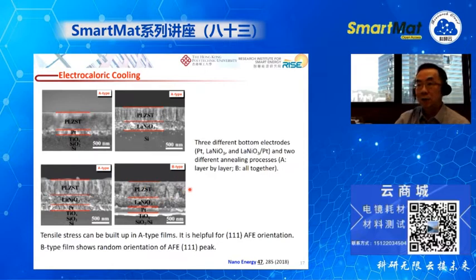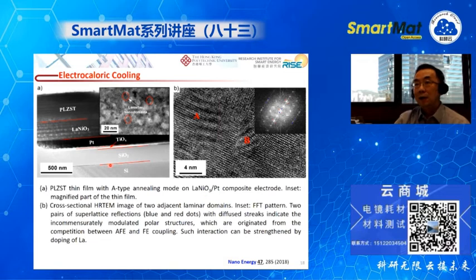So we use two different types, and later we do some detailed microstructure characterization, and we do find some superlattice diffractions, with diffuse streaks, which also indicate the polar structure. And we found this lanthanum doping can strengthen the interaction between the antiferroelectric and the ferroelectric coupling.